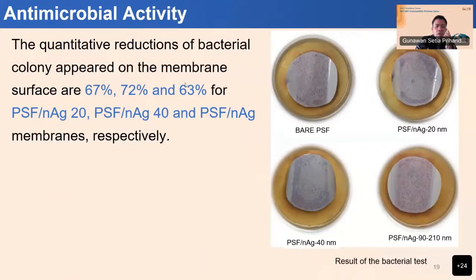Okay. And then for the microbial activity, you can see here that we have four types of membranes: the bare PS membrane without any nanoparticle, and then the ones with nanoparticles of 20 nanometers, 40 nanometers, and so on. Almost all the membranes have bacteria growth on the surface. But when we use the image to check how much bacteria appear on the surface, we can see there is some reduction, about 70% of bacteria reduced on the membrane surface.